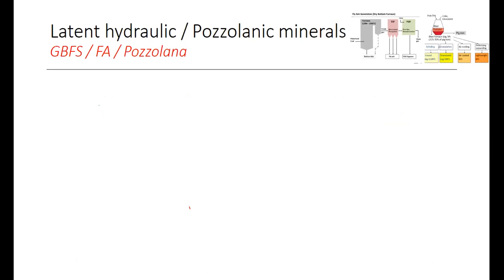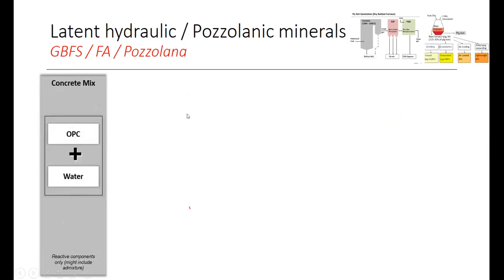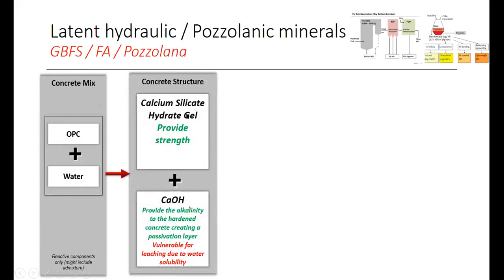Then we'll come to some mineralogical matters, how latent hydraulic materials like slag, or pozzolanic materials like fly ash or pozzolana, are acting. Basically, as we discussed previously, if we put OPC with water, we get calcium silicate hydrate gel, which provides the required strength, along with calcium hydroxide or portlandite. There are pros and cons of this portlandite. The positive is that it provides the required alkalinity, because calcium hydroxide is an alkaline material. It provides the required alkalinity to the hardened concrete to create the passivation layer, which is a good side.